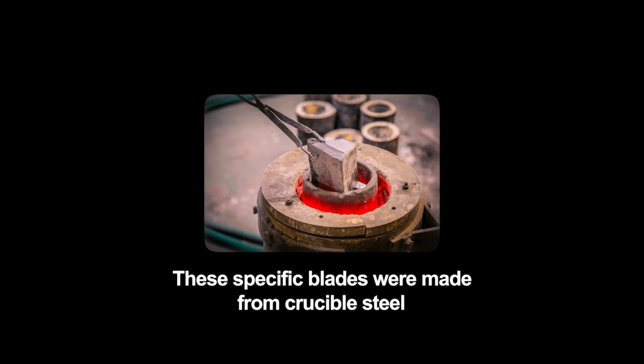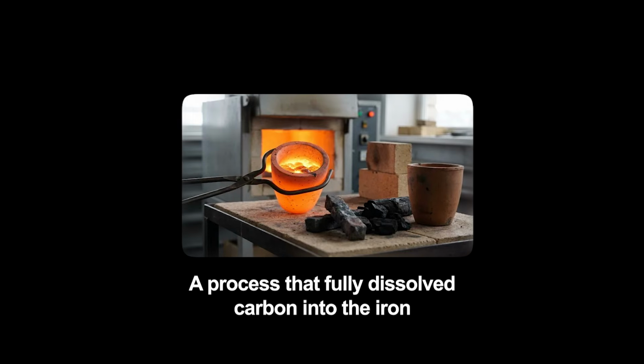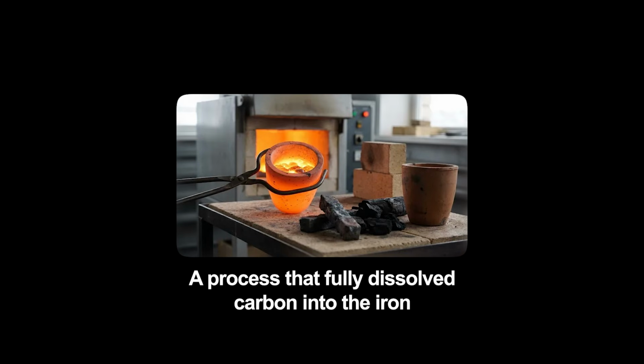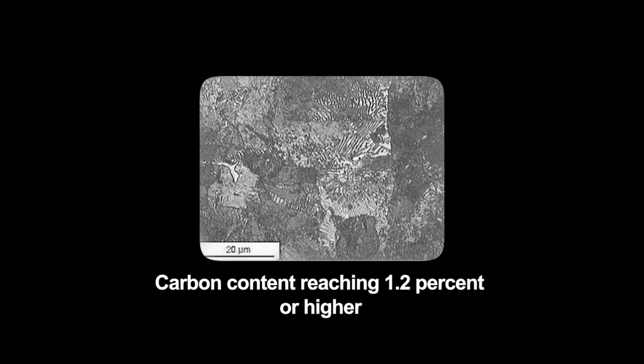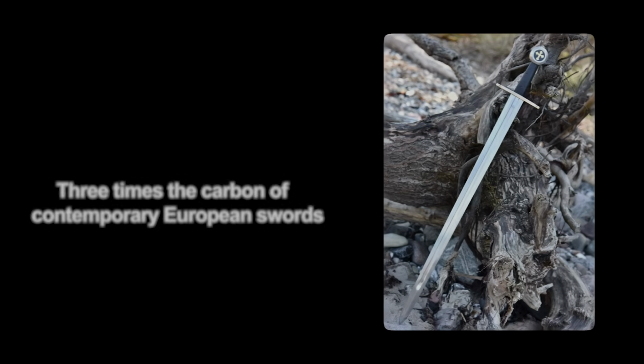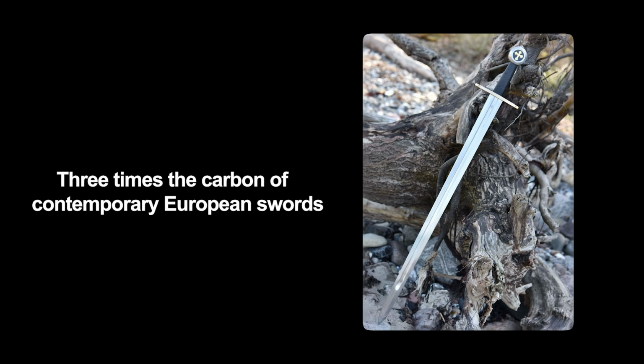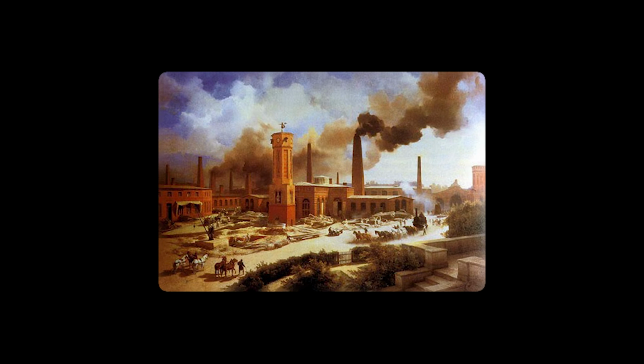These specific blades were made from crucible steel, a process that fully dissolved carbon into the iron, eliminating slag and impurities entirely. The result was a homogeneous, high-carbon steel with carbon content reaching 1.2% or higher, 3 times the carbon of contemporary European swords, a material composition that would not become standard in Europe until the Industrial Revolution.